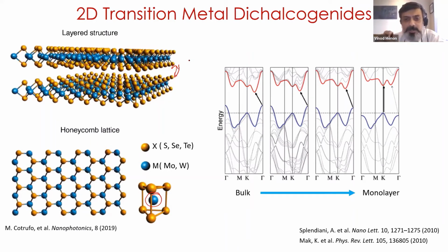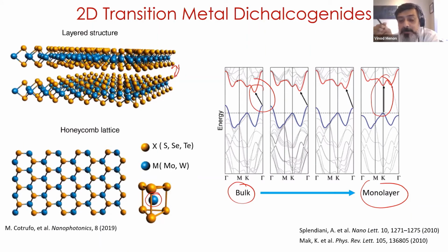What is also interesting about these materials is when you go from a bulk to a monolayer limit, you go from an indirect band gap material to a direct band gap material. And this also happens at the K point in your crystal lattice and not at the gamma point. This also introduces some intriguing properties called valley polarization. So all you're doing is you're taking this bulk crystal, you start removing the layers, and once you go down to the monolayer, this thing starts emitting light.